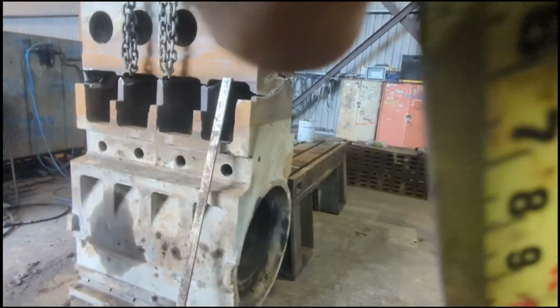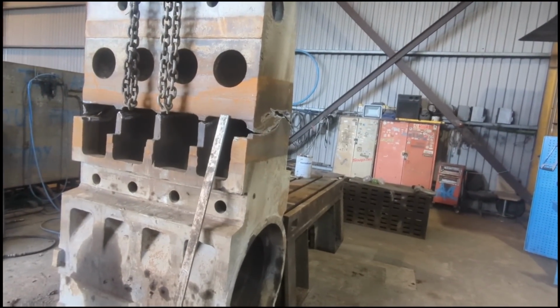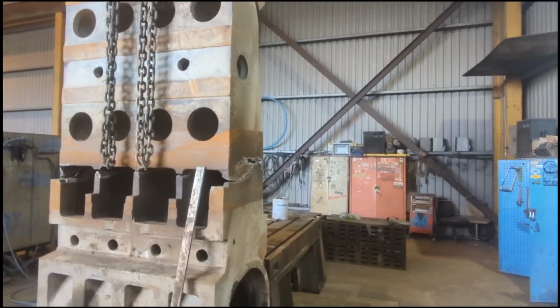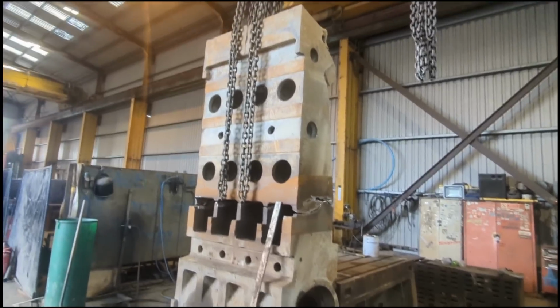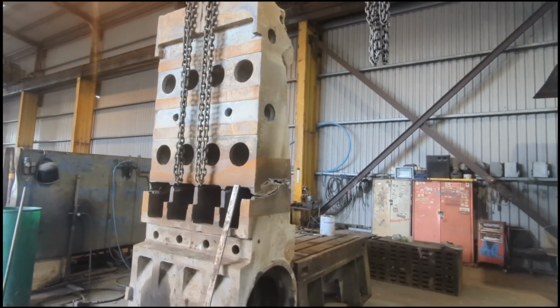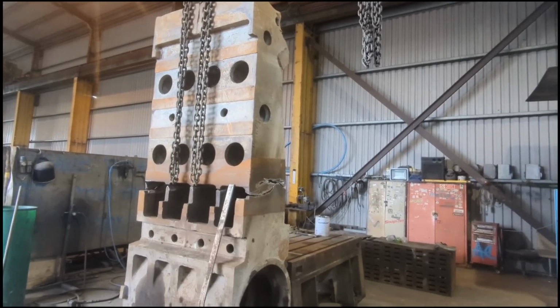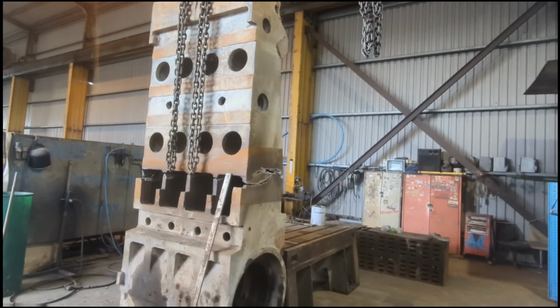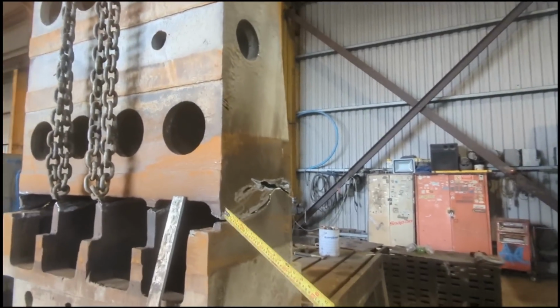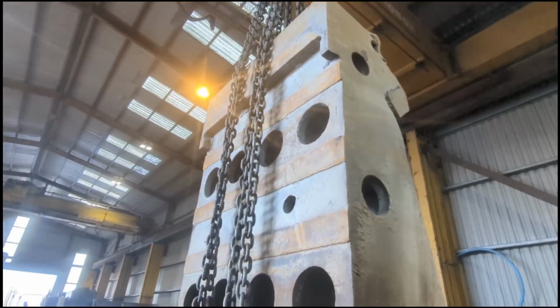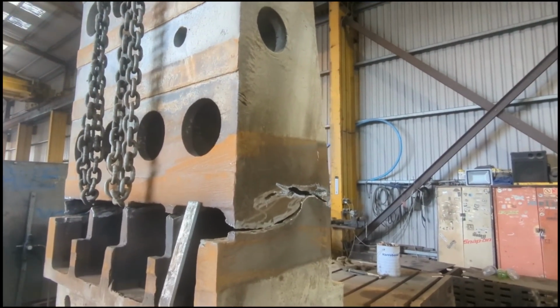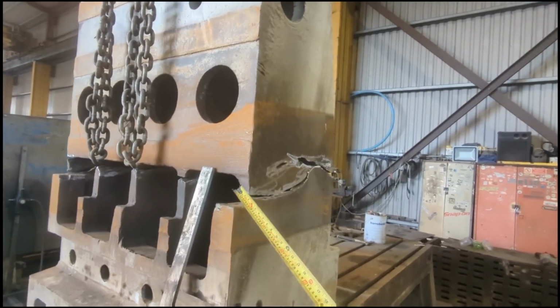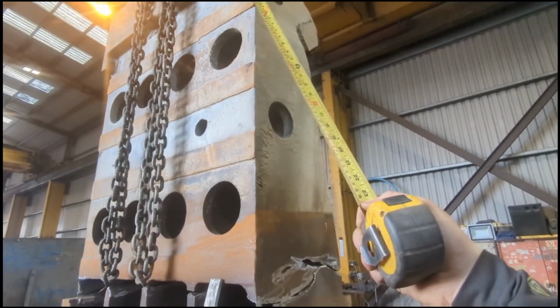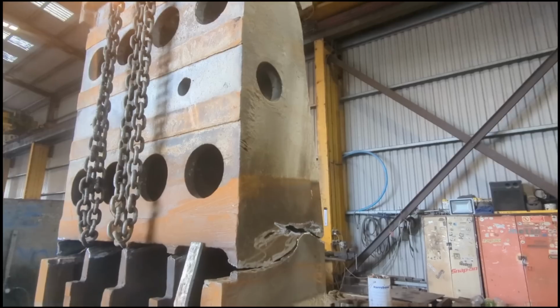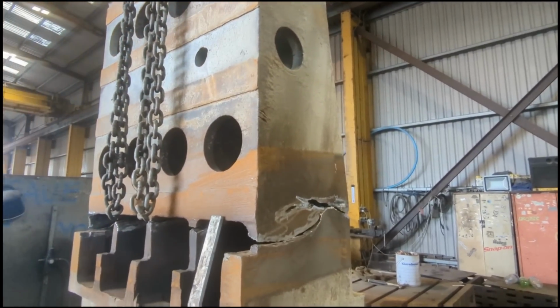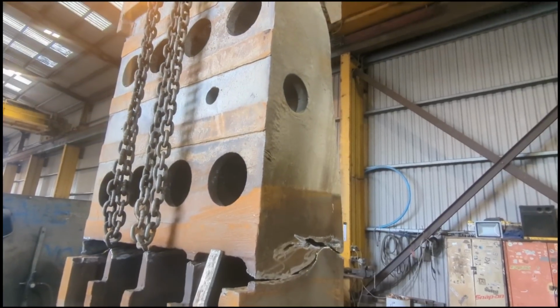So with this initial test fit, a few datum points to check. This jaw is a bit more of a prick compared to the other one, because on the other one the wear part just sits on a flat surface. This has recesses that the replaceable jaw liner sits on, and the distance here and up there is obviously going to be affected by the crack, the break. So I need to ensure that this distance and that distance up there stay the same when repaired. I'm going to measure between those and then go out and measure the jaw liner to see if they're anywhere near the same, or if I need to shim it.